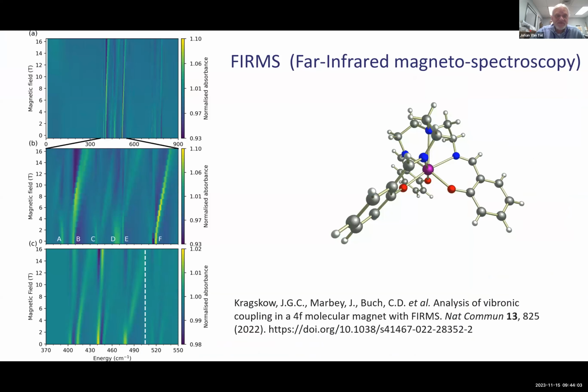And then something that we also have available at the Mag Lab, if you want to go to even higher frequencies, is using far infrared spectroscopy. You do that as a function of the field, and if you're smart about your background correction, because these infrared spectra have all kinds of interferences in your system, but if you treat these well as a function of the magnetic field, you can correct for all the things that are not field dependent. And you can see the field dependent splitting of your energy levels directly in your frequency range. And that is very useful for looking at interactions with phonons and all these kinds of things.